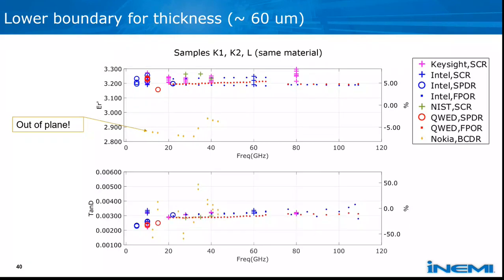So with that, I bounded these by the lowest thickness, the highest thickness, the lowest permittivity, and the highest permittivity of the real materials we measured. Here we have the lowest thickness we measured at about 60 microns. You can see at the top, those points in the real part of permittivity are all very tightly spread.